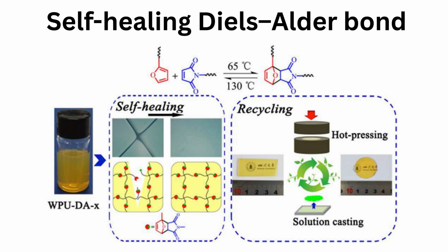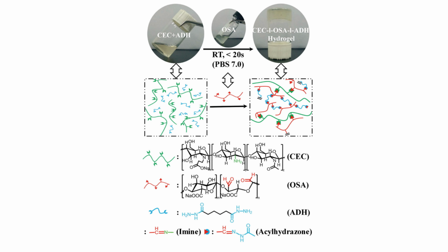This also possesses recyclable properties. Following a self-healing process at 130 degrees Celsius for 30 minutes and subsequently at 65 degrees Celsius for 24 hours, the overall performance of the polyurethane film was restored. Reversible acyl hydrazone bond. The reaction of hydrazide with a carbonyl group, aldehyde or ketone, creates a reversible acyl hydrazone bond, which breaks and then reforms in response to aniline or acid stimulation.